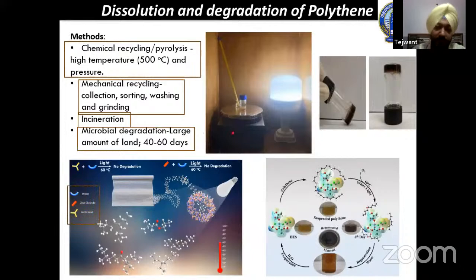Here it's important to mention, zinc chloride is solid at room temperature, lactic acid is solid at room temperature. But once you mix lactic acid and zinc chloride in appropriate ratio, heat it up to around 80 or 90 degrees Celsius for 7-8 hours, and cool it down, it remains liquid at room temperature. This liquidity arises from the strong intermolecular hydrogen bonding between the hydrogen bond donor and hydrogen bond acceptor, such as zinc chloride and lactic acid. When you mix two solid components and they become liquid at room temperature through hydrogen bonding interactions, such solvents are called deep eutectic solvents. They exhibit properties similar to those of ionic liquids.